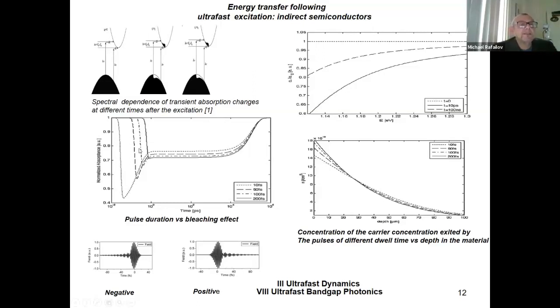And so I asked the question many times at this conference: did you try to use different pulse widths? Because the excitation picture is completely different. You don't have this big deep drop at the relaxation process, at the bleaching process, when you have a pulse above 100 femtoseconds.